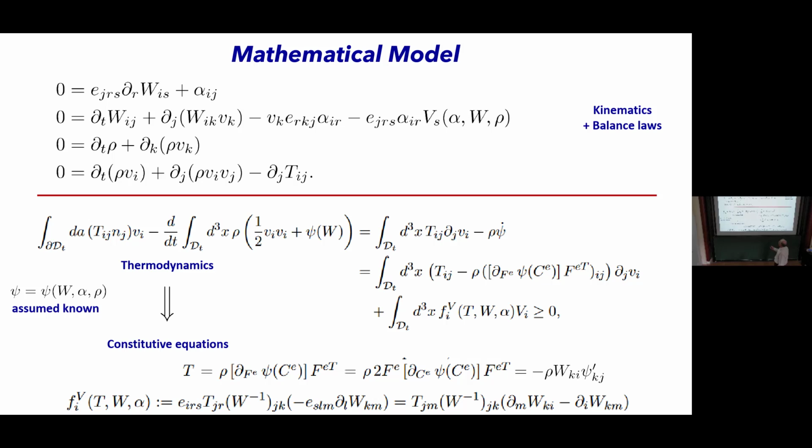If this were elasticity, this fellow is... my slides will have equations, blah, blah, blah, right? Don't focus on that. This is just a curve. So this is the curl. The curl is non-zero. If it were elasticity, it would be zero, because every curve under deformation has to map to a closed curve. When you have a dislocation, as we just saw, a closed curve opens up.